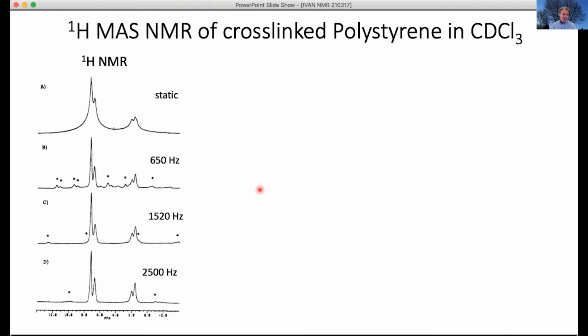For that, we go back to a technique we worked on a number of years ago when I was a young postdoc. We realized that if you have lightly cross-linked polystyrene gels, static NMR gives you very broad aromatic and aliphatic signals, but a little bit of magic angle spinning of the swollen gel will collapse these patterns.